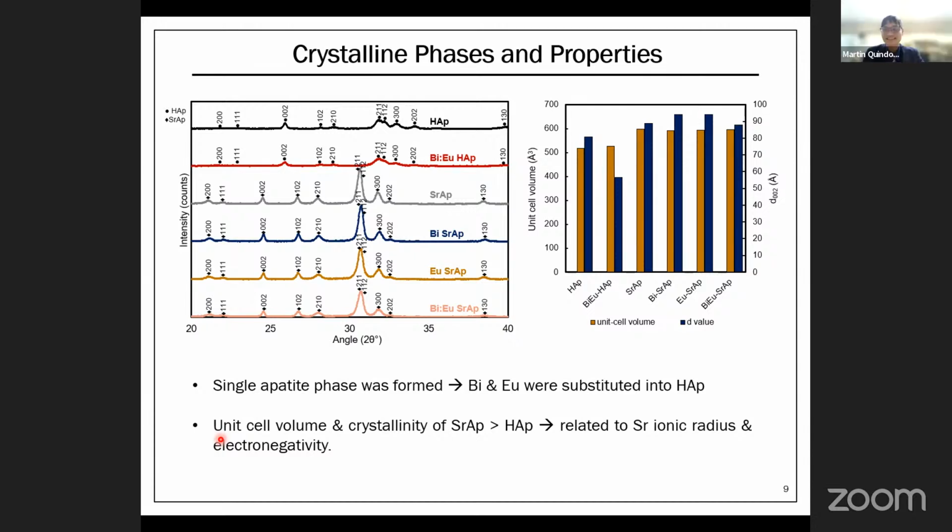So it is difficult to compare the DFT data and your experimental data. Yes, the difficulty is because I formed the nanocrystals at 120 degrees Celsius, not at a high temperature. So the data that I can get experimentally is not as much as what I need for the DFT. Yes, thank you.